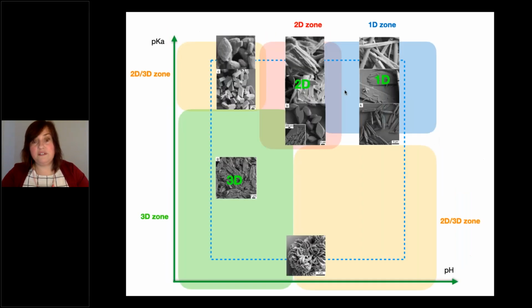And when we overlaid their images with these predictions, we found pretty good agreement. So in the top right, there's a 1D zone. Most of the particles formed here are about 1D. And then everything gets a little bit wider in the 2D zone, so we get to platelets. And then in the bottom part is clearly stuff that is 3D. And then also the yellow regions are between 2D and 3D.